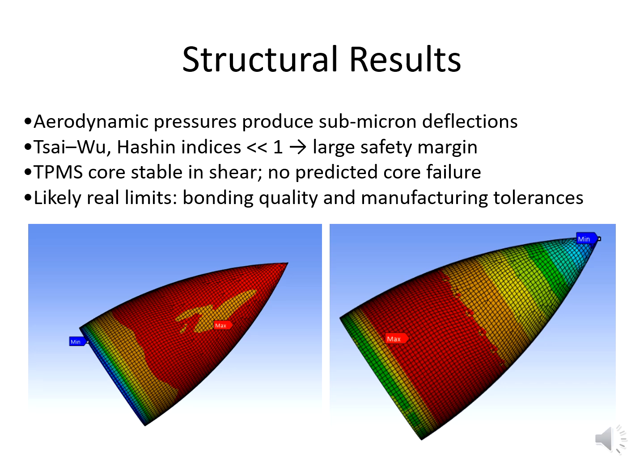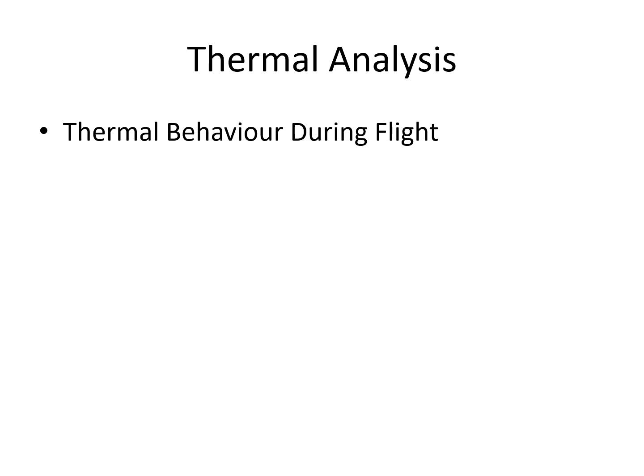The likely limiting mechanisms are not global bending, but rather local phenomena such as core crush, adhesive failure, or interface debonding during extreme loading or manufacturing imperfections. This gives us a clear direction for future physical testing and refinement. Transient thermal simulations are planned but were not completed within the available project timeframe. They will be included in the next phase of this work.